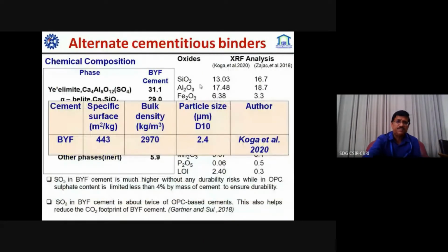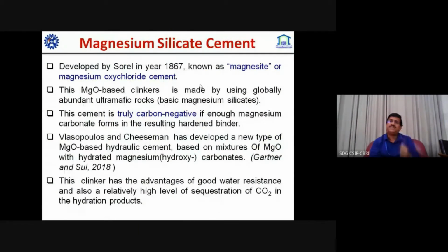So these are the different types of materials, and different researcher groups including CSIR and CBRI are working on other types of material. I have said this is magnesium silicate cement. It was developed very long ago, in 1867, basically as an MgO based clinker, and magnesium silicate. This is abundantly available all over the place, and when it is utilized, a lot of carbon dioxide from the atmosphere it captures and sequesters. By that it enhances the strength. So that is very advantageous, with very good water resistance and a relatively high level of sequestration of CO2 in hydration products. So that is why we have said it is carbon negative.